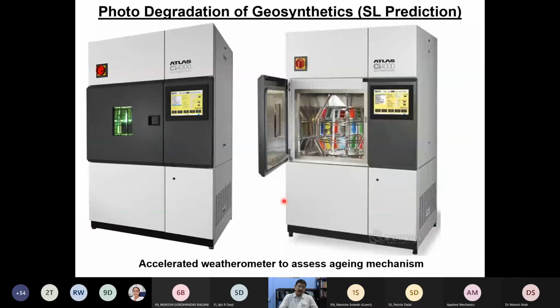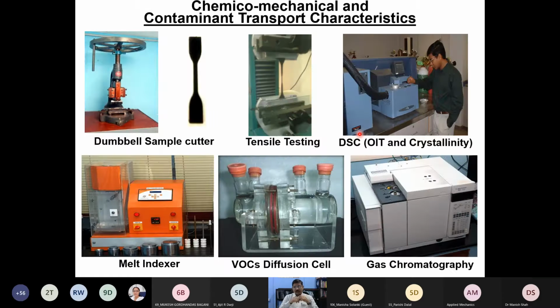Recently, we got the Xenon arc weatherometer. Instead of using UV light alone, we simulate more or less the entire solar spectrum using this state-of-the-art equipment, where you can spray water, and we can control the humidity and temperature. After subjecting the sample to these environments, at a given exposure time, we take out the specimen.